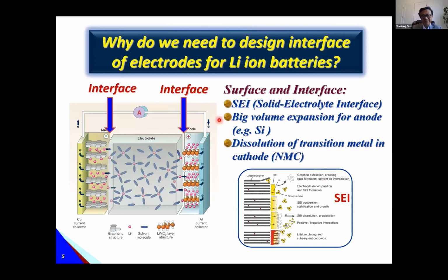So I'll talk about interface; actually, we already talked about that a lot. In the liquid-based electrolyte, we know a lot of things happen at the interface, for example, SEI. And if you're using silicon, there is volume change. And if you're using layered structures, transition metal dissolution always happens at the interface. So here it is a liquid.